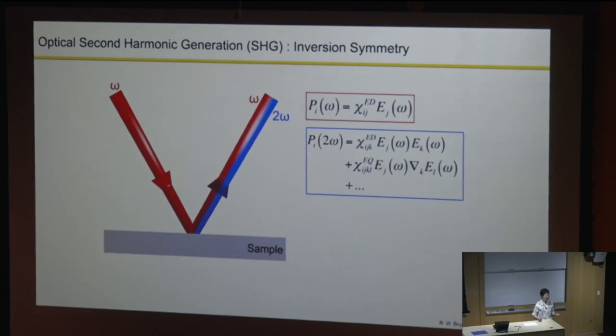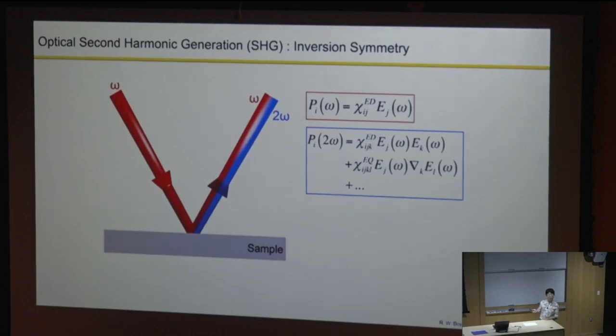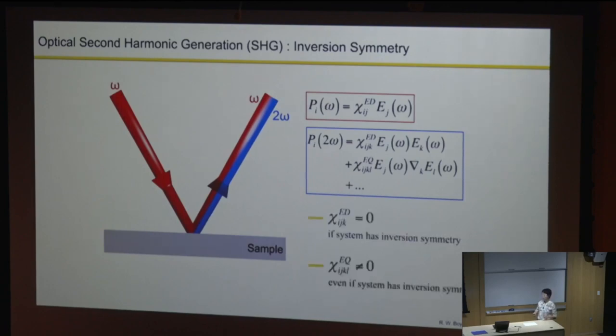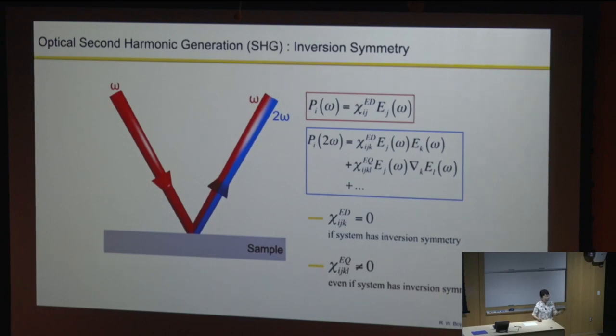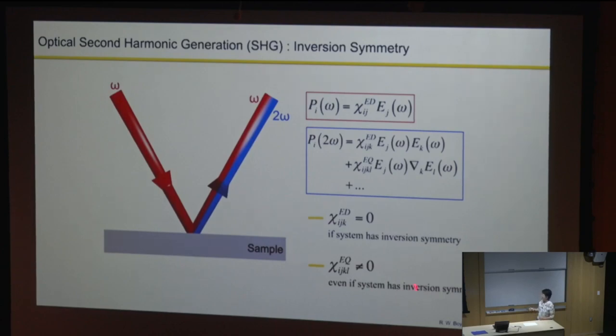People later realized you have different radiation sources. Even though the leading-order electric dipole is gone by the inversion symmetry, you can still have the next-order electric quadrupole, magnetic dipole, or even octupoles. SHG is there for all materials—it's just that whenever you have inversion symmetry breaking, you have a big signal through the electric dipole process; and whenever you have inversion, you have weaker signal from the higher-order processes. We are going to utilize this channel to study phases that actually have inversion.